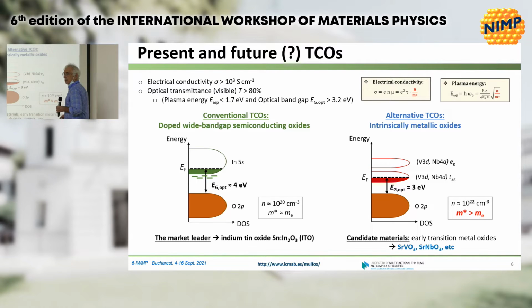The idea that we are trying to pursue at this moment is a different strategy: to take a metal in which we do have a gap, and the electrons here have a heavy mass. If the electrons here have a heavy mass, this number is going to be very large, and even if n is very large, 10 to 22, it is not a doped material, it's an intrinsic material, the plasma frequency can be very small, well, down to the infrared. And this idea of trying to use materials with a heavy mass of the electrons in the conduction band is somehow defined by the word correlated transparent metals, assuming that the correlation is responsible for the heavy mass of the electrons.